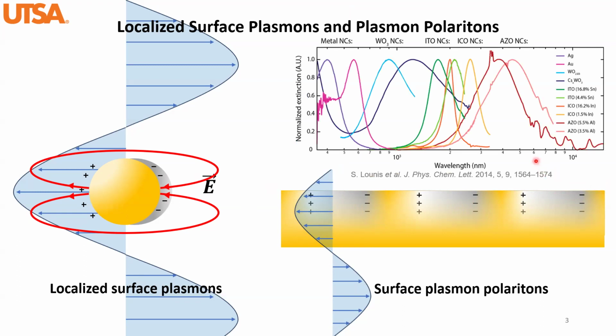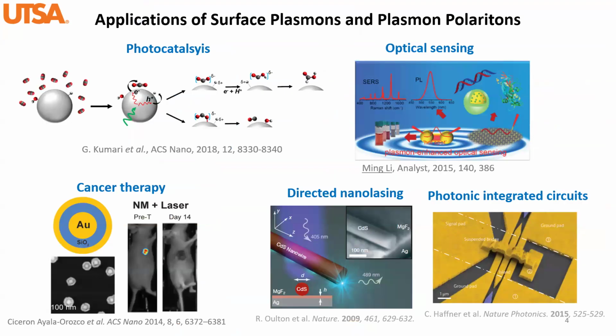Typically, gold and silver are the most frequently used plasmonic materials. But since a decade ago, people have been looking at different materials for surface plasmons, and they find that doped semiconductors, including oxides and sulfides, can also support surface plasmons. It's just a matter of which frequency or which wavelength it is. So gold and silver support surface plasmons in the visible range, and sometimes gold supports them in the near IR. But oxides support surface plasmons in the IR or far IR in this case.